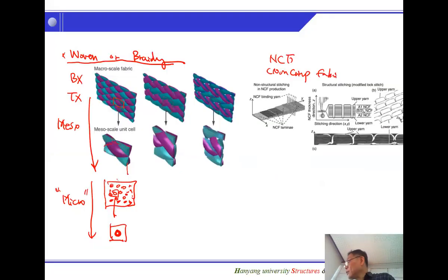Okay, as you can see, this one has an out of plane undulation. Out of plane undulation is in the z direction, and out of plane means an undulation in z direction. And so this can be very weak under compression.